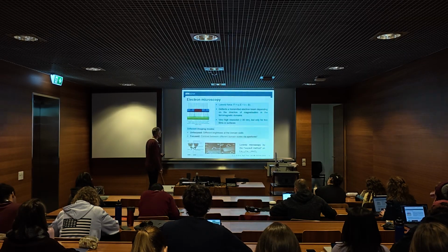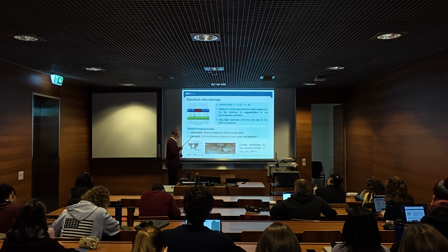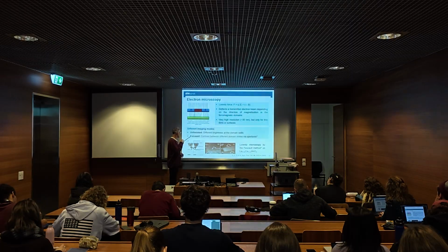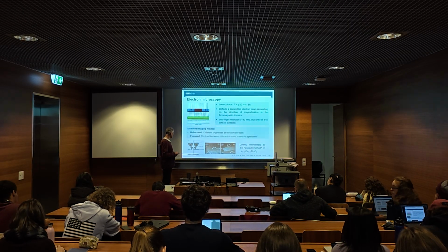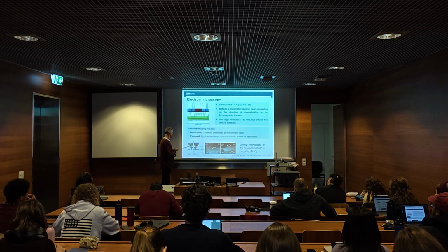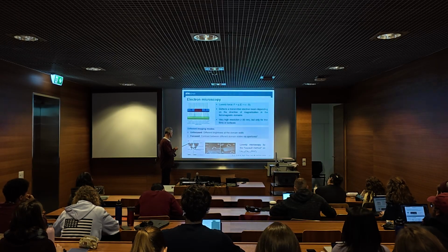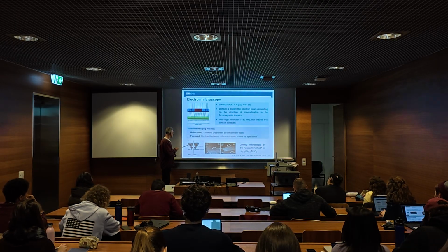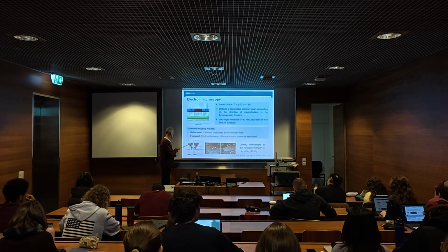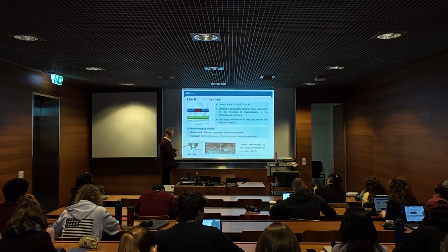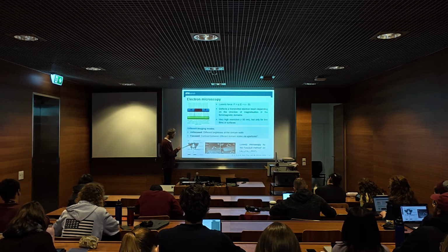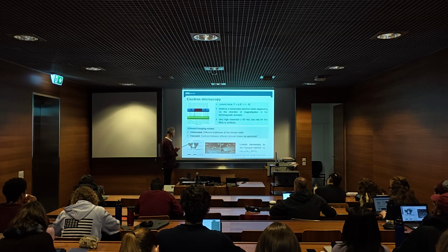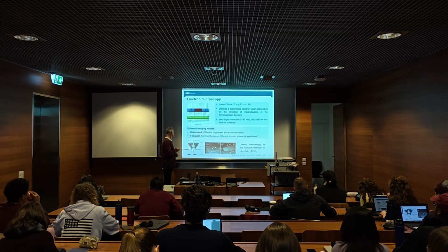But there's also a way to see the domains directly if you focus your electron beam, which you can do with magnetic field lenses, kind of. Then it's the principle that is shown down here. So we have the deflection of the electron beam in the two different domains for the two different domain states. And then you put a lens there, an electron lens, and that focuses all the, say, plus m electrons onto one spot, and it focuses all the minus m electrons on one spot.